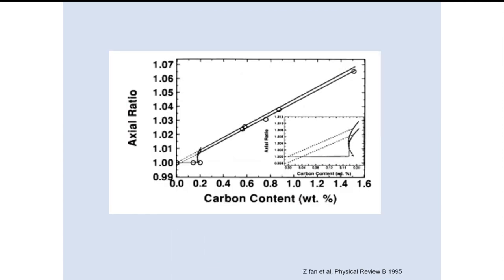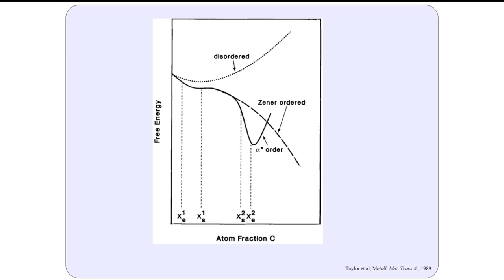To summarize: the C/A ratio is more than one when carbon concentration in alloys is more than 0.2 at room temperature. If the carbon concentration is less than 0.2, the crystal structure of the displacive product or displacive ferrite should be cubic. There is another interesting feature: when carbon atoms are ordered, the structure undergoes conditional spinodal decomposition at low temperatures or below the spinodal line, resulting in the formation of carbon-depleted and carbon-rich regions. If carbon atoms are disordered, there is no miscibility gap in the iron-carbon diagram.